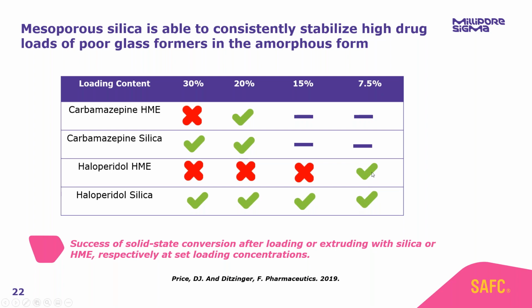Now, as it turns out, haloperidol has a very low dose, so around 5 milligrams to 10 milligrams. So a 7.5% drug load is still a feasible formulation. But we all know that the average dose is around 200 to 400 milligrams. So imagine how many tablets that patient would have to take if we could only stabilize 7.5% of that molecule in our hot melt extrusion formulation.